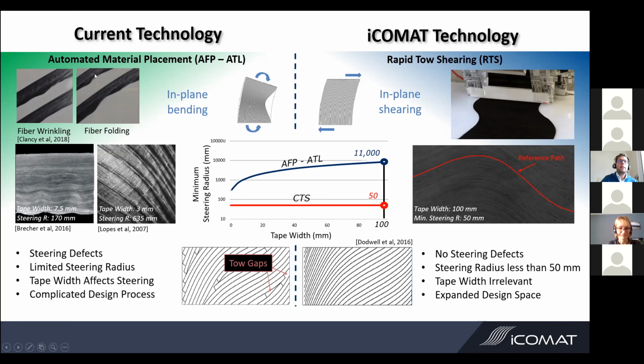Another point is, with the existing technology, when you try to place tapes side by side onto a surface, curved tapes that is, you inevitably end up with features like tow gaps and overlaps, which are pretty much unavoidable. But with iCOMAT's technology, because we're shearing, we are able to passively change the width of the tape as we deposit it. So the width increases or decreases, and that's coupled with a thickness increase or decrease.